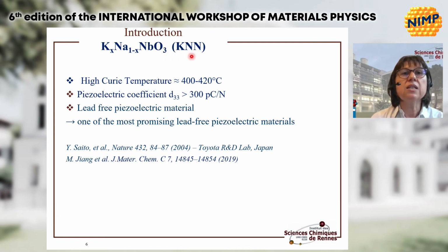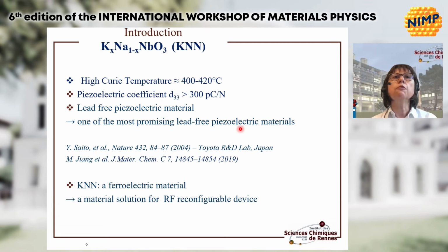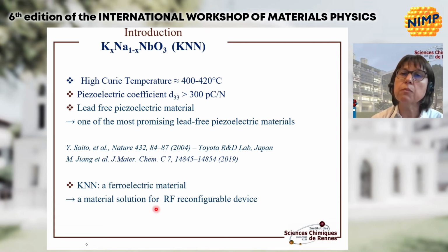That is the perovskite of the KNN system. This material is well known for high Curie temperature, but also for high piezoelectric coefficient. And today, it is considered as one of the most promising lead-free piezoelectric materials. But this material is also a ferroelectric material. And in this case, it's possible to tune the dielectric permittivity, which gives a material solution for high-frequency reconfigurable devices.